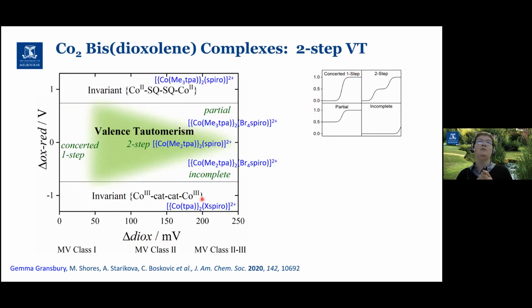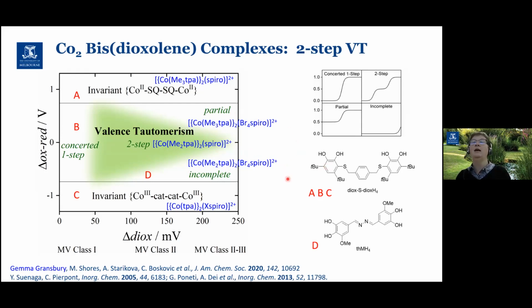We can actually map the values of all of our complexes there. So for instance, the plain TPAs that are stuck in the cobalt-3 catechol form, the ones that do the VT transition, the bromospiro, the communication just seems to be a little bit too much that we don't see the two-step transition that we want. So it's only in the case of the plain spiro that delta diox is just a little bit less that we seem to be sitting in that two-step regime. And we can also plot on this diagram some literature complexes from other people. So for instance, this one here, we've got a sort of a thioether linkage between the two dioxelene units. And in that case, they only see a concerted one-step transition, and that correlates with insufficient electronic communication between the two dioxelenes in their bis-dioxelene ligand.